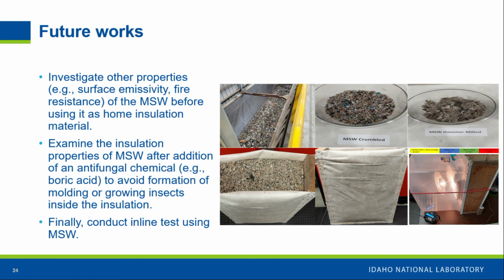One of the things usually used is boric acid, which is a fine particle. As I claimed, with the finer, smaller size material, we are making higher porosity, so we will get better thermal properties. But if we use this fine boric acid, the pores might clog. So we don't know how that will behave after adding the boric acid. That's the thing we want to test as well.